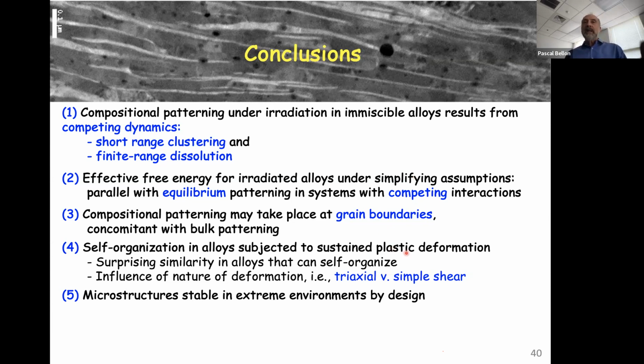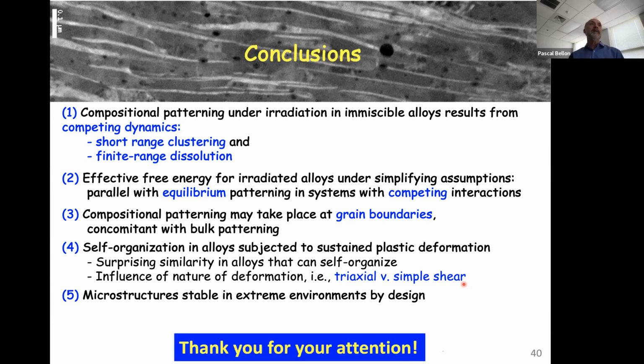That patterning can also take place in alloys subjected to severe plastic deformation, sometimes resulting in isotropic structures, sometimes lamellar structures. And then in many cases, both for alloys under irradiation and under severe plastic deformation, these dynamically stabilized nanostructures can perform very well under extreme environments. And because they are stable, they are the steady state where the system wants to be under those extreme environments, these microstructures will not change with time. And so it is certainly an intrinsic advantage where we would have a resistance to extreme environments by design.